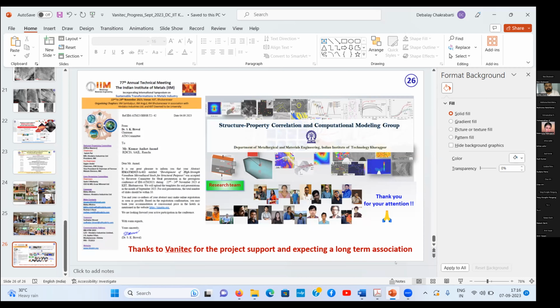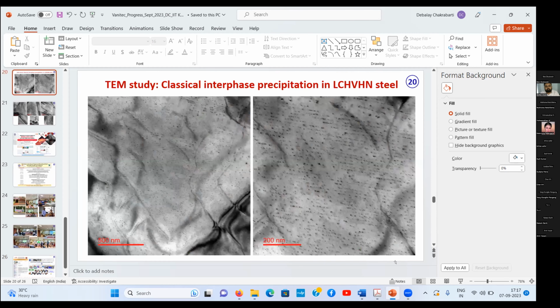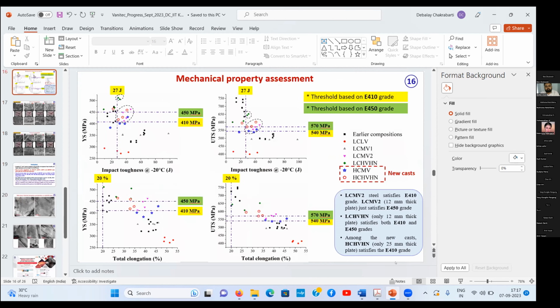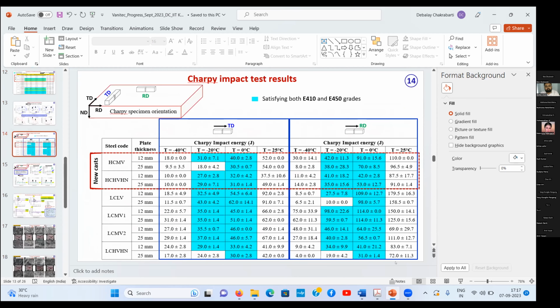850, yeah. Why I'm asking is, according to my experience, one ought to be getting somewhat higher Charpy values at 0, at least, than what you're reporting there. Quite a few of them appear to be pretty borderline in the 40 joule but below region. Our experience is we're getting at least 80 to 100 joules in that temperature range for those thicknesses, using a good vanadium nitrogen combination. I just can't remember what your nitrogen level was.